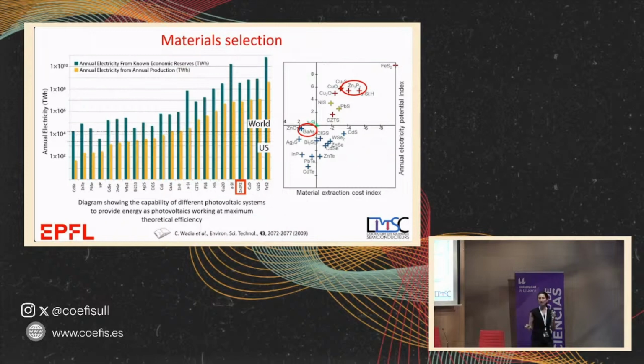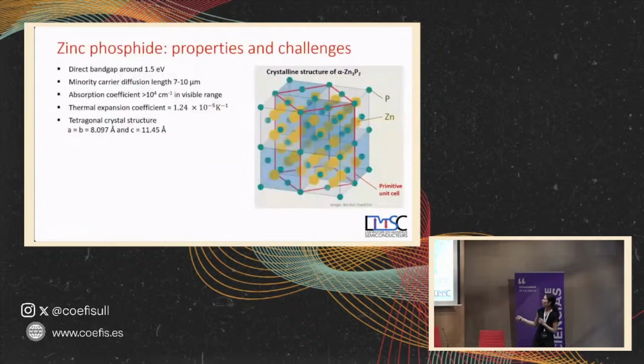Some people had attempted this material in the 60s and 70s, but there was really very little. What we knew is that this material has a direct bandgap in the region that it should have for photovoltaics. It has a good absorption coefficient, and it has a thermal expansion coefficient that is very different from any material. So if you grow it on a substrate, you will have cracks. It has a tetragonal structure, which means it's difficult to grow on anything.